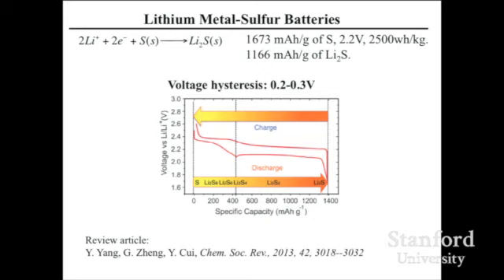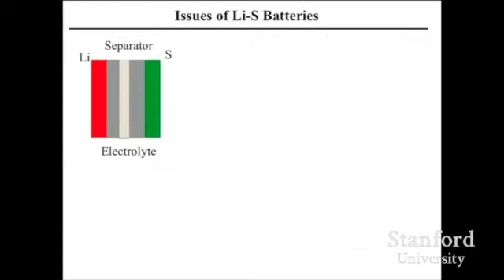Sulfur can be charged and discharged right here. This is the voltage versus capacity. Once you put lithium into sulfur, they start to form a polysulfide phase, soluble in the electrolyte, later becoming lithium sulfide. And this is very, very hard. People have worked on this, the sulfur cathode, for a few decades.